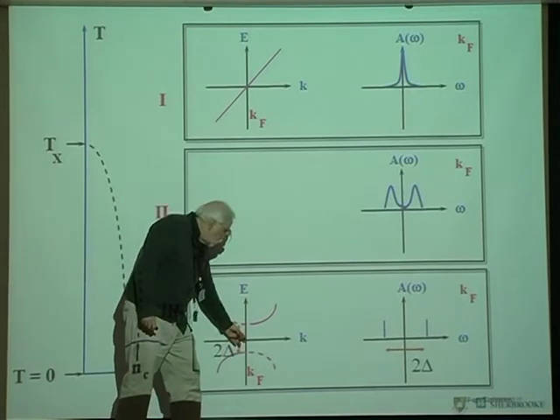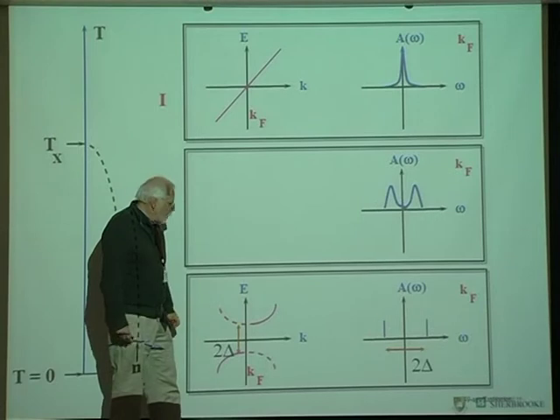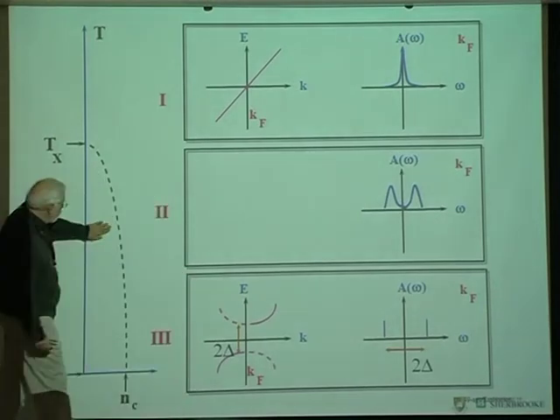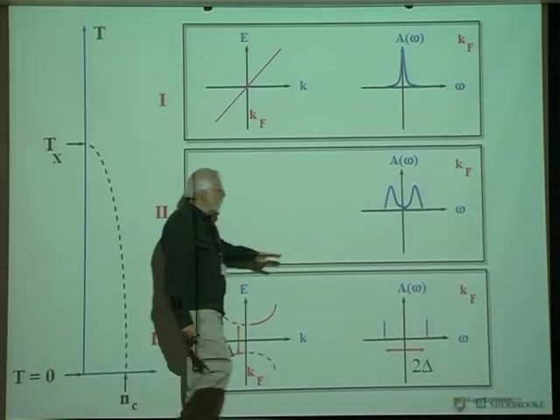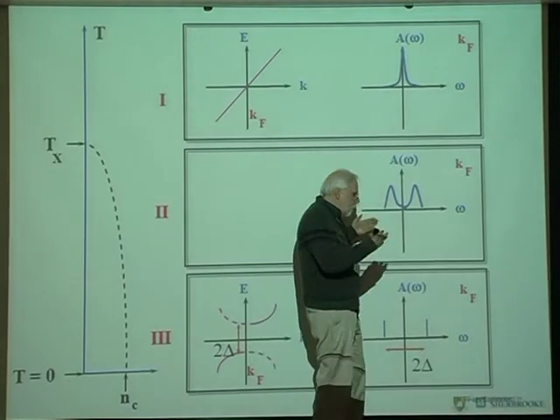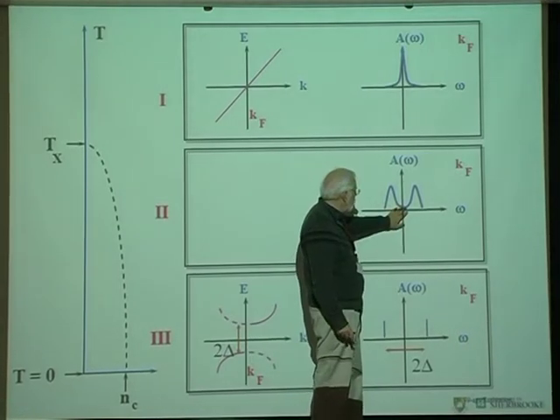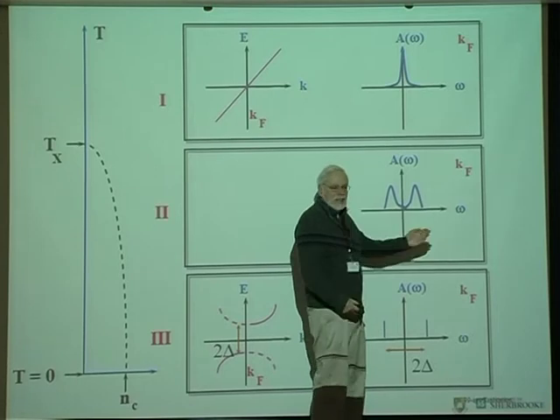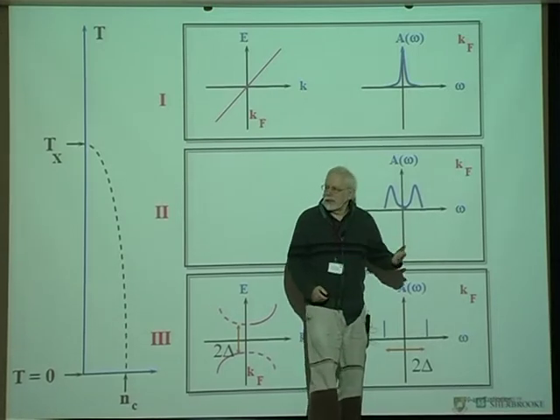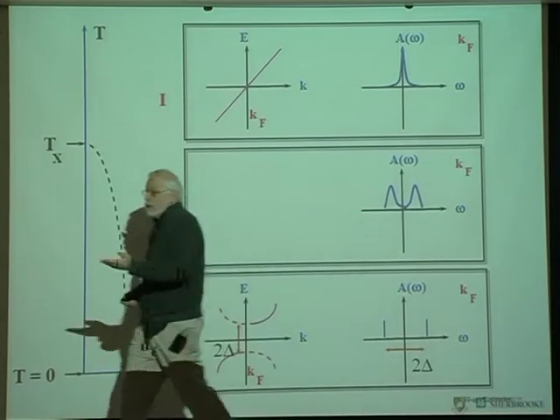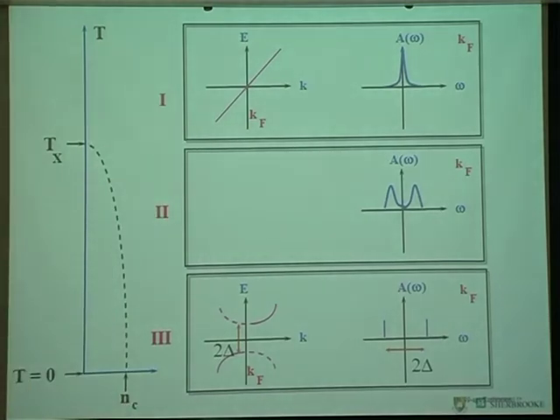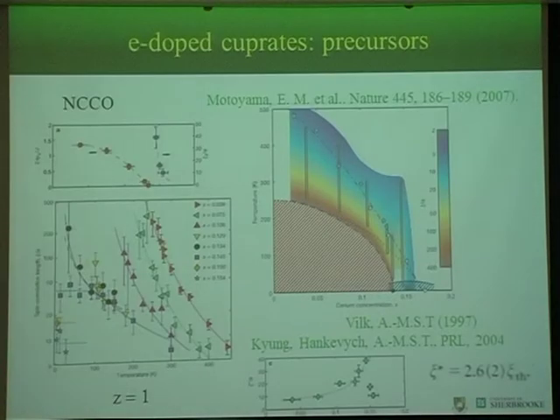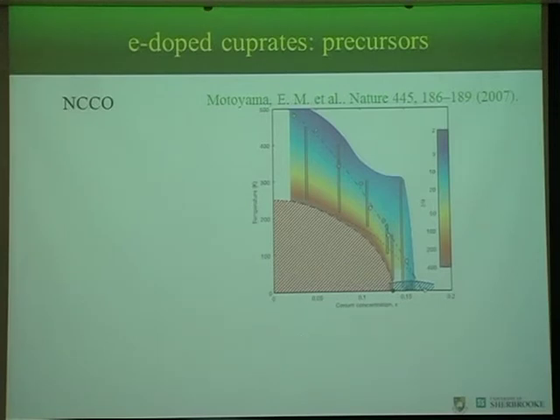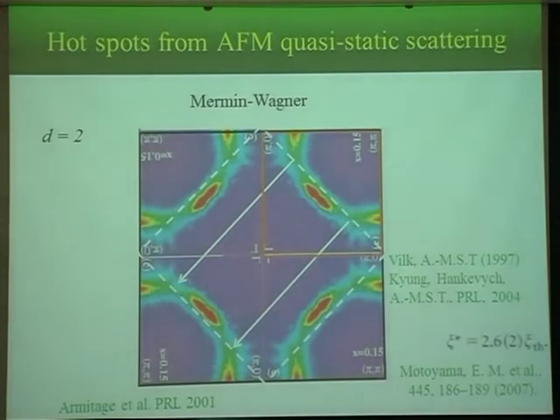So in other words, you remove states from the Fermi level. Now, if you're in this intermediate region here, this pseudogap region, when you are at the intersection with the antiferromagnetic zone boundary, you remove weight and you put it elsewhere. It's not at the Fermi level. It's now lower or higher. So this is how you get this. Okay.